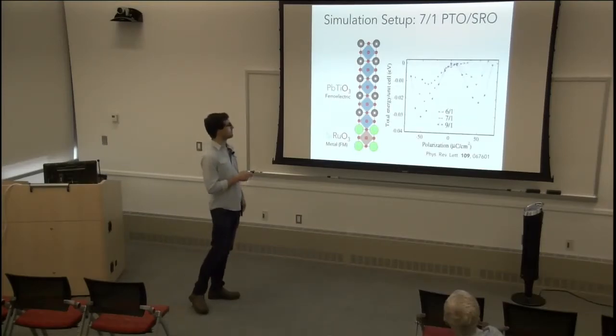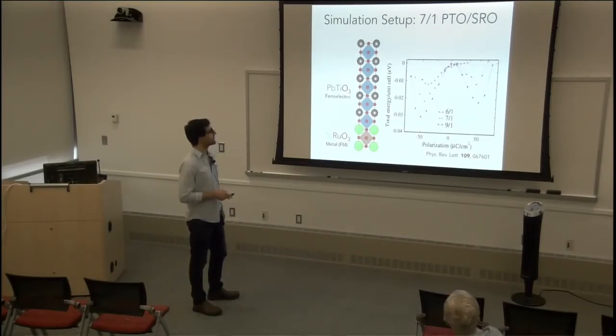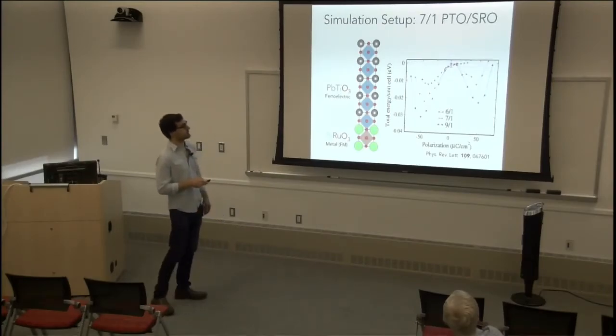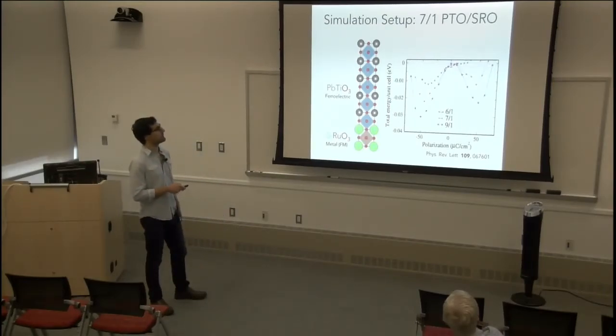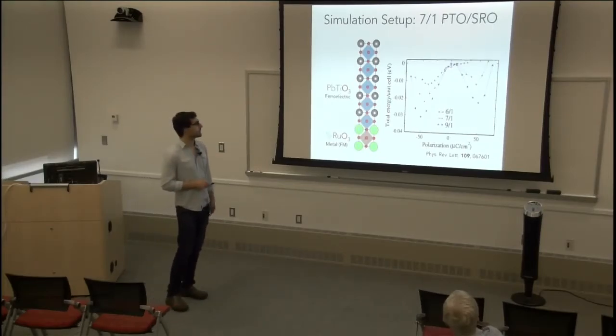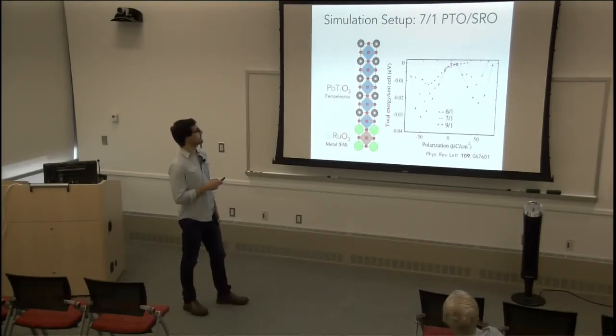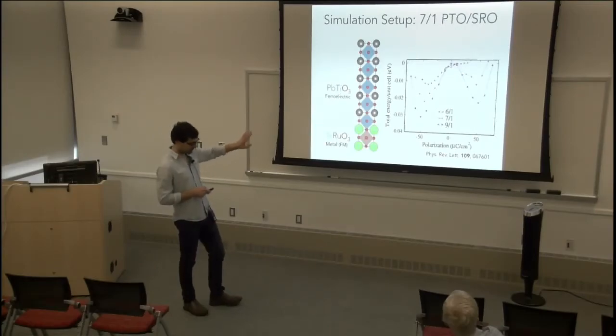You can see this better here, where this is the energy versus polarization. And this is the amount of PTO unit cells, the amount of SRO, strontium ruthenate unit cells. You see that for different concentrations of lead titanate, you get a slightly different double wall. And the pattern here is that as you increase the lead titanate unit cells, ultimately you should end up with a symmetric double wall potential. But clearly I'm doing 7-1, so you see the wall is pretty asymmetric already. And you're not doing any defects yet. I'm not even talking about defects.